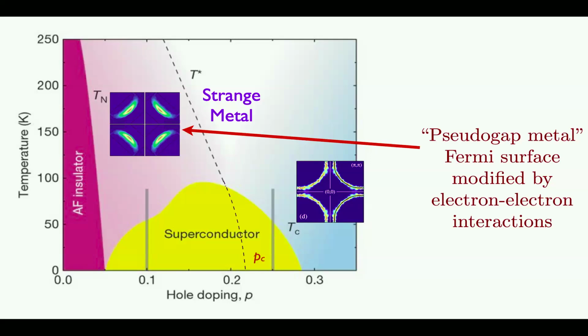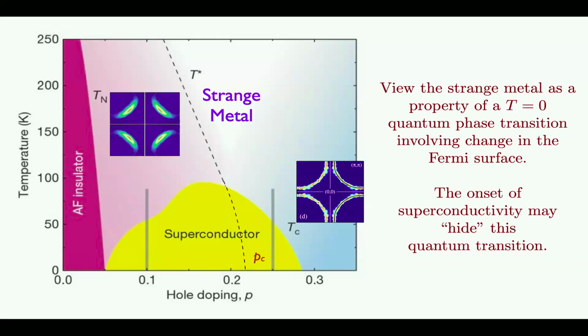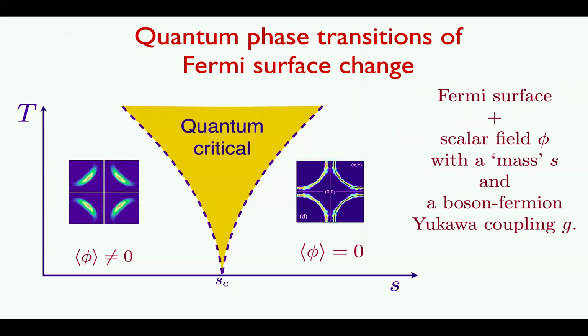But let me just make a few remarks about the general setup. Once we agree that the most important thing here is the fact that there are two different metals, and at zero temperature maybe the strange metal will disappear, and you could somehow hide the superconductivity, then you'd have a quantum phase transition which involves a change in the Fermi surface. So let me just get rid of the superconductivity and set up this kind of generic quantum critical phase diagram, where you have two different Fermi surfaces with a zero temperature quantum phase transition.